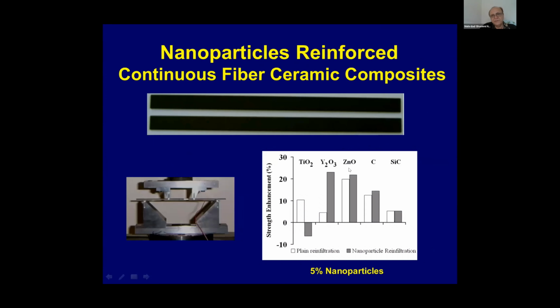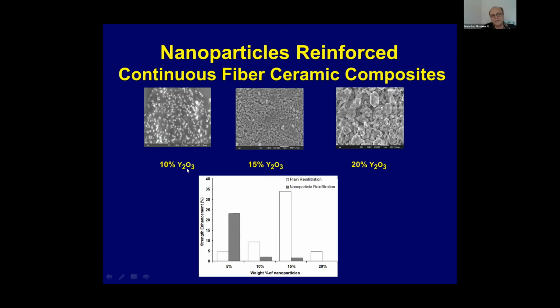So we showed that when we use different nanoparticles named here, titanium oxide, yttrium oxide, zinc oxide, carbon, and silicon carbide, you get a property improvement. The open bars are plain infiltration, and then solid bars are nanoparticles. It means this is a PIP technique, polymer infiltration pyrolysis technique, that you should pyrolyze a number of times to increase the density. So that's the PIP polymer. We are saying that whether you should have nanoparticles or not, that's why we showed here. We showed that certain nanoparticles perform the best, for example, yttrium oxide. And then we pick that, increase the property from 10%, 15% to 20%.